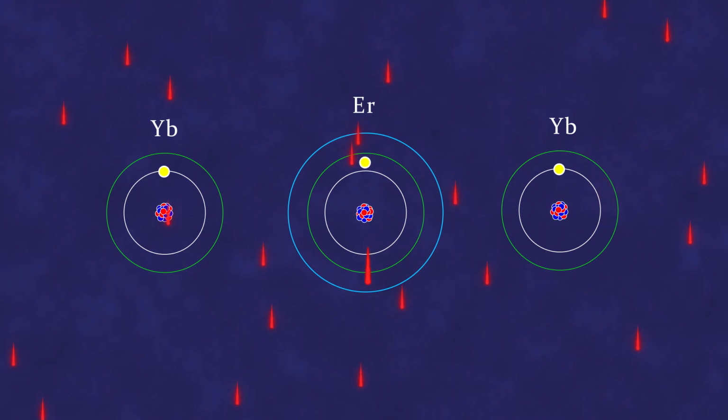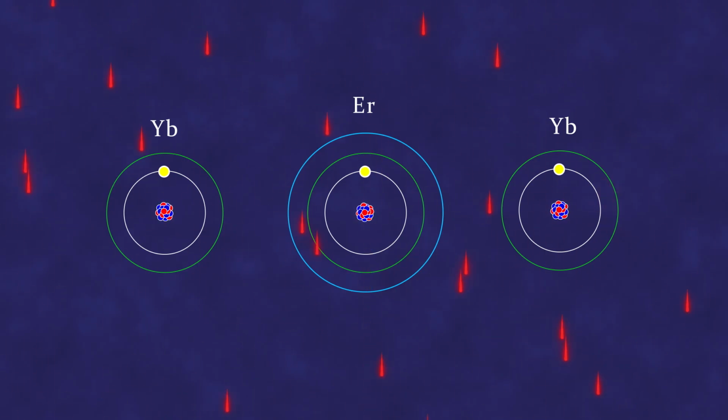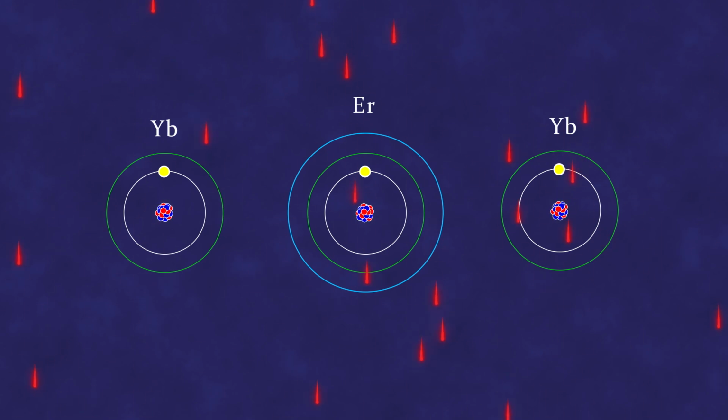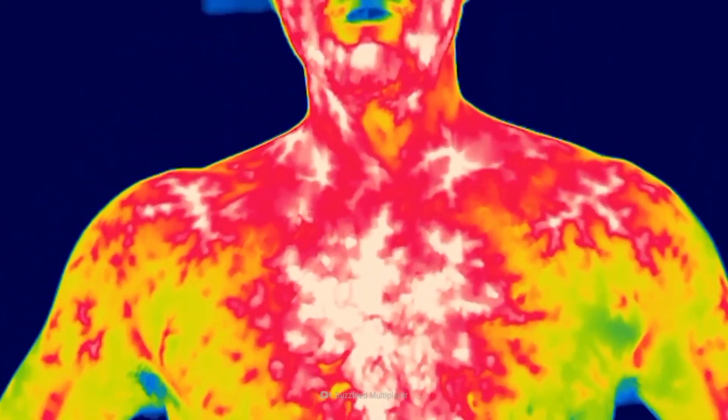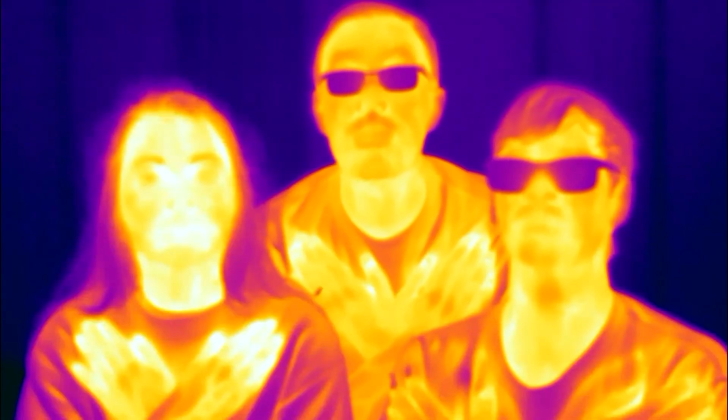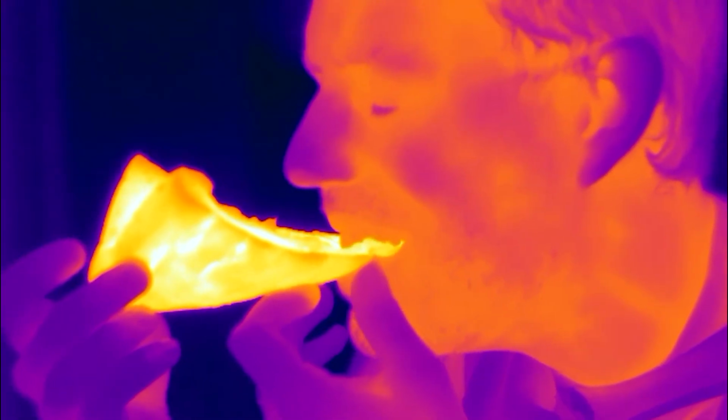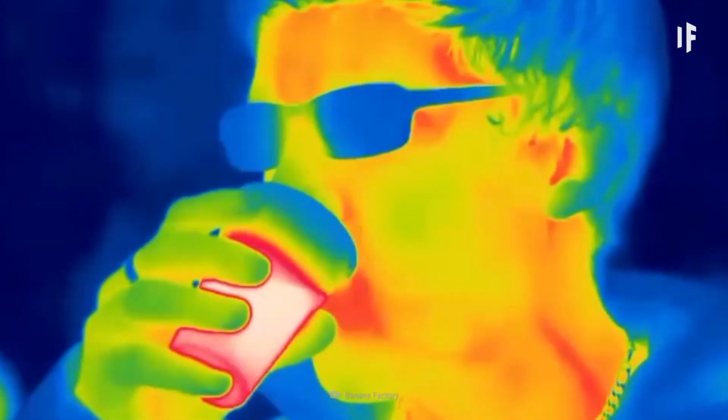again via Förster transfer. In general, the efficiency of upconversion in the case where two photons are converted into one is proportional to the photon flux density passing through the upconverting crystal. And the photon flux density is directly proportional to the square of the amplitude of the electromagnetic field oscillations at the wavefront. For streams of infrared radiation emitted by objects at room temperature, the efficiency of upconversion in a ytterbium-erbium pair amounts to mere hundredths of a percent, and the upconverted visible light will be far too weak to be detected by the human eye.